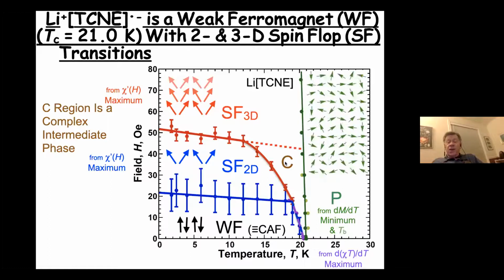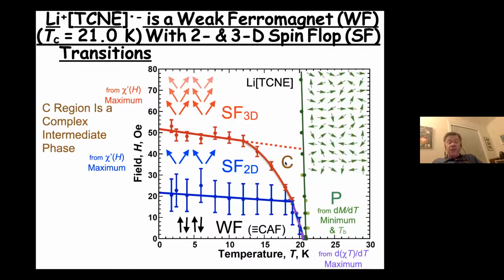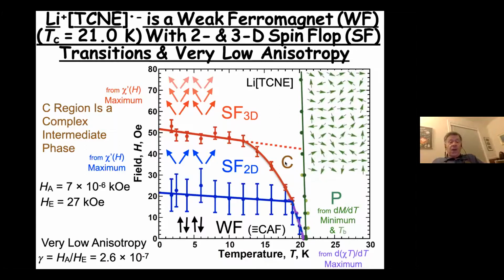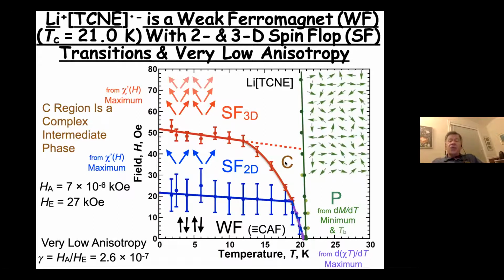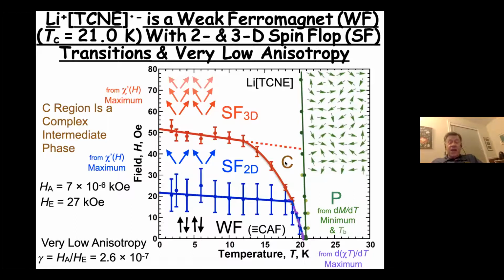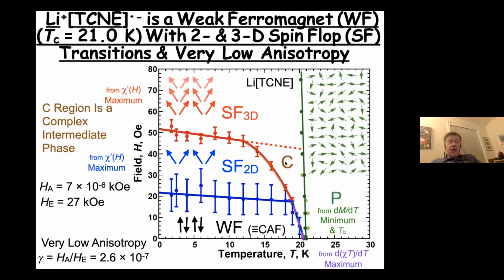So we've generated the phase diagram for this material. We've also determined the anisotropic field to be a fairly small value of 7 times 10 to the minus 6 kilo-oersteds, and the exchange field at 27 kilo-oersteds, and the ratio of the anisotropic field to the exchange field gives you a figure of merit for the anisotropy for the system, which is an incredibly low value of 2.6 times 10 to the minus 7.